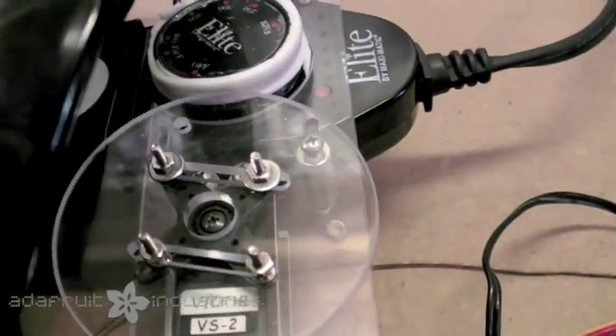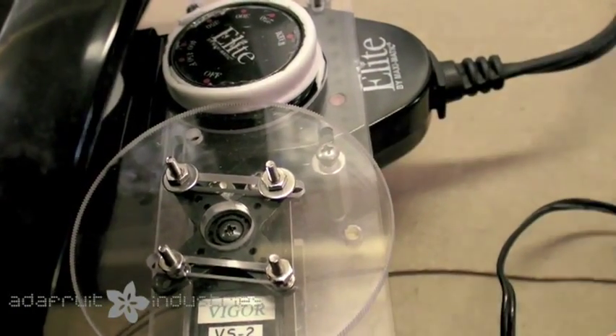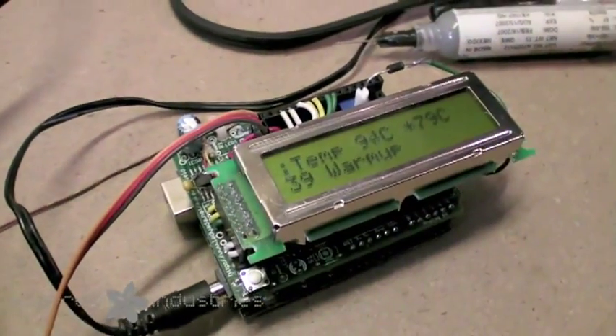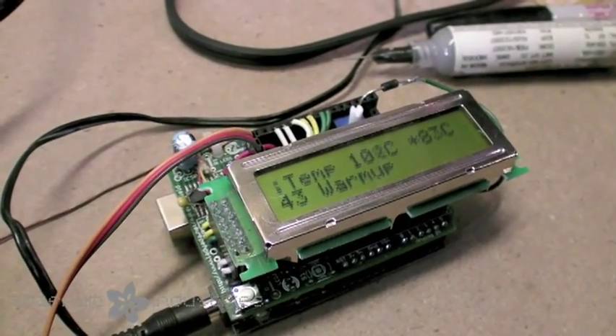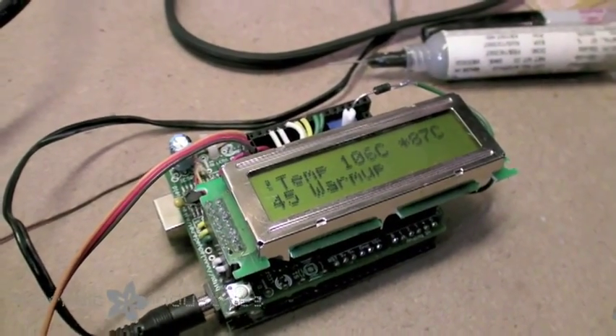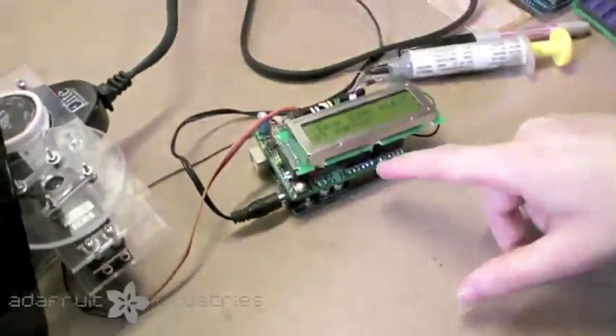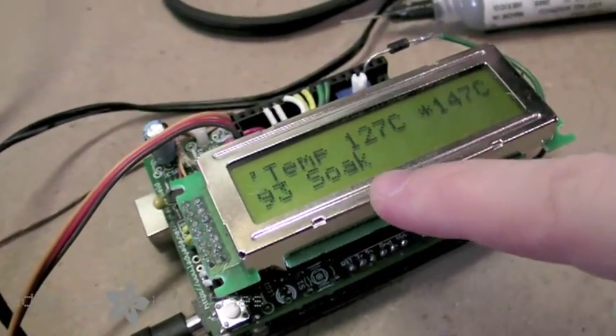First we do the warmup. That's the first part of the curve, and you can see this is slowly turning. The warmup basically takes the board up to about 120 degrees Celsius, and that just kind of gets the board ready for the reflow - some chemical processes occur at that temperature. At around 90 seconds of warmup we go to the soak phase.